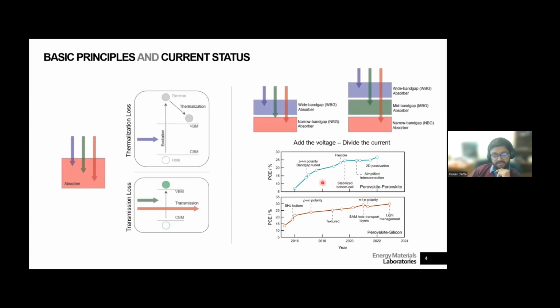The big development was the coming of these lead-tin narrow bandgap perovskites, which allowed bandgap tuning, which started somewhere here. And then these devices, because they are thin film, you can use them as flexible devices. So that comes in here with pretty good efficiency. So the climb in perovskite tandems has been much more significant, much more exciting than the case of perovskite-silicon tandems.